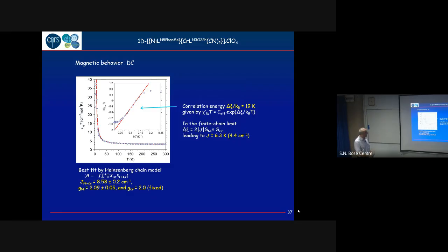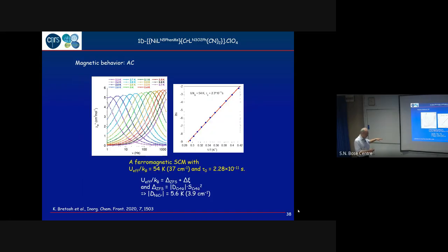But this is also obtained from the blue data you can see here, that are the experimental data. To have something like that, you can only confirm the interaction. But we have also the MH. I don't know if I show it or I don't show it. But for magnetization, we have also information. It's ferromagnetic or antiferromagnetic. So if it is antiferromagnetic, it goes down, so the value will be smaller.